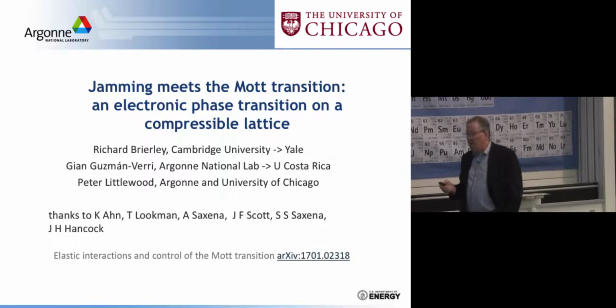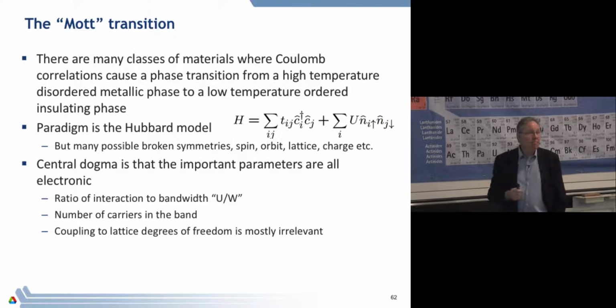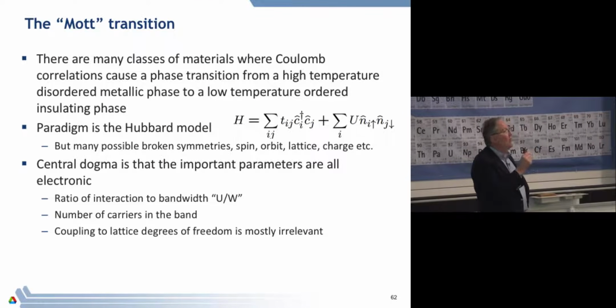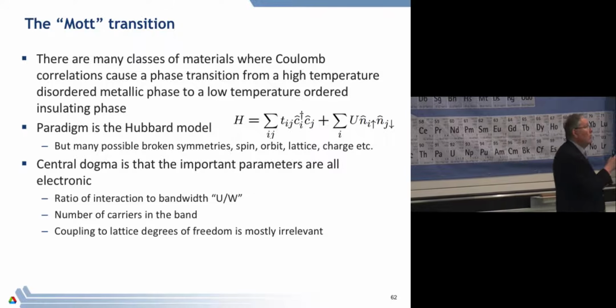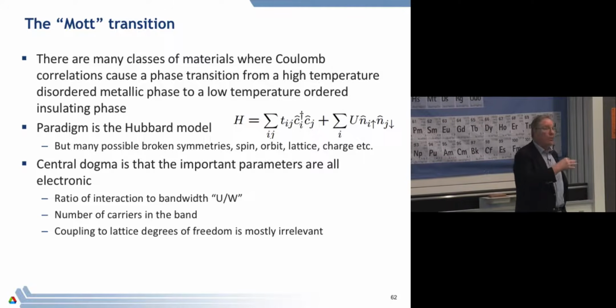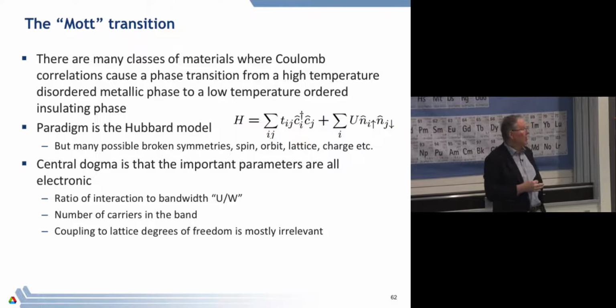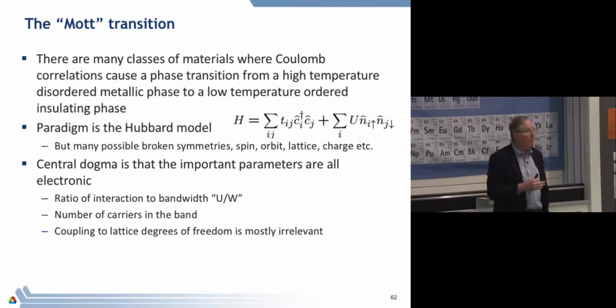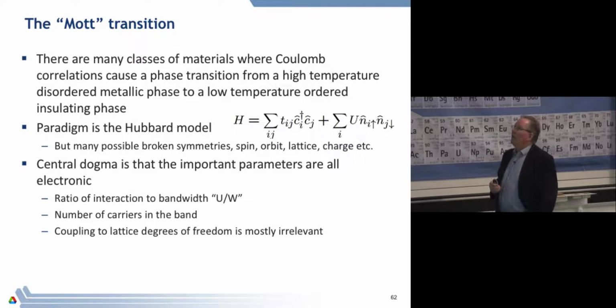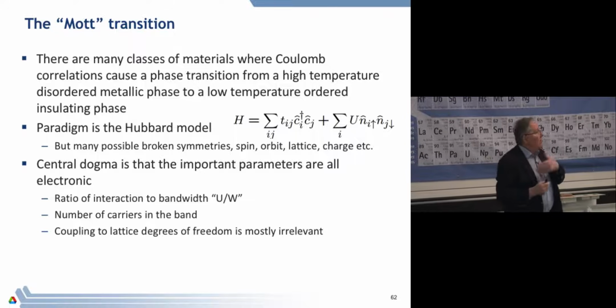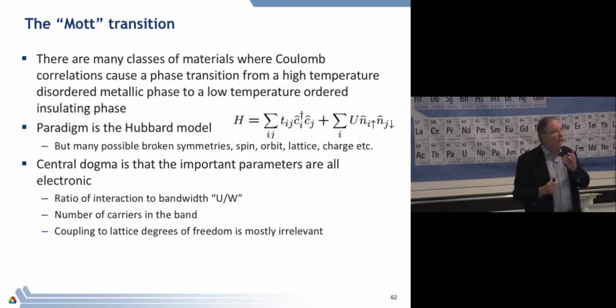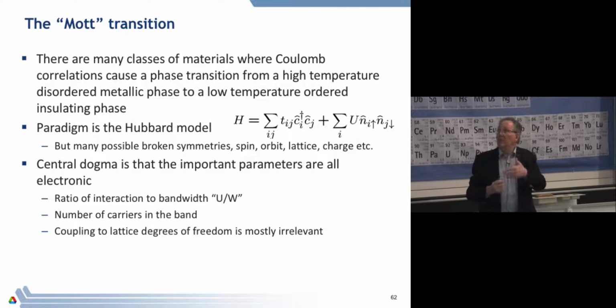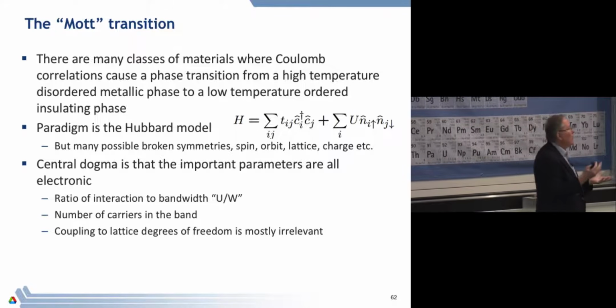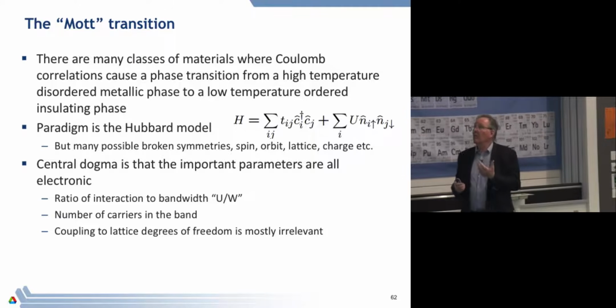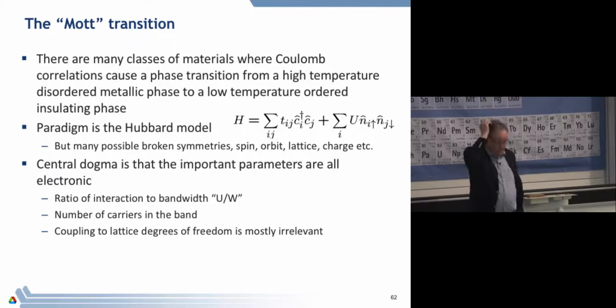And why might one matter? Okay. So I just introduced the idea that one of the problems that we're having with wanting to use battery electrodes made out of lanthanum nickelate is that lanthanum nickelate is in fact an insulator. Okay. And that is a classic case of a correlation-driven phase transition. It's not something that you would find in the standard band structure. It happens only because the Coulomb interaction is important.